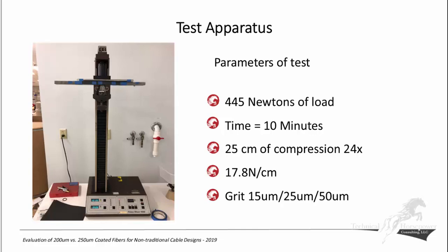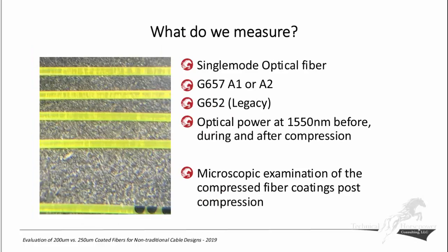So the end result is we had all of this information put together. We set this parameter up as our initial set of tests with the 3 different versions of this. This is what we measured. And here you see the post-compression results of one of the fibers under test. And we use single-mode optical fiber, primarily G657A1 or A2, as we were able to get it from our suppliers. And we used a legacy fiber, G652.